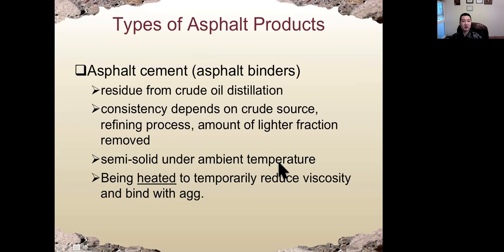Let's look at asphalt cement first. So asphalt cement is the first type and the most commonly used one. It is residual from crude oil distillation. The consistency, which is how easy the asphalt cement can flow, depends on the source of the crude oil, the refining process, and also the amount of lighter fraction removed. It is semi-solid under room temperature. To liquefy it, it needs to be heated up. So when we heat up the asphalt cement, the viscosity will be lower, so we can mix it with sand and coarse aggregate. So that's the first type, asphalt cement.